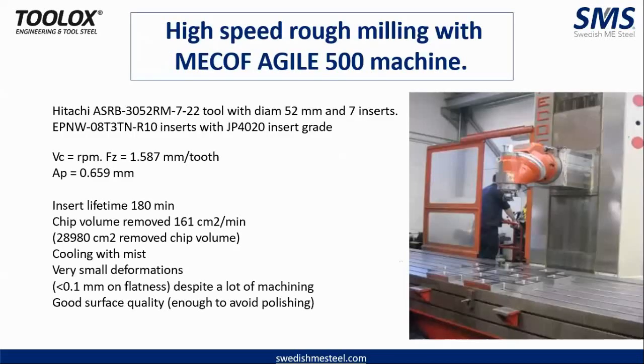So this is a high-speed milling machine being used. You can see the insert lifetime is 180 minutes. It is removing chip volume of up to 161 cubic centimeters per minute. Even after this heavy removal of material, the deformation is very, very low. You can see it's less than 0.1 mm on flatness. So you need not do any kind of polishing after the machining. It's directly put into use.